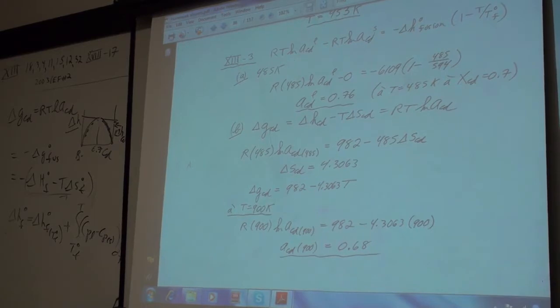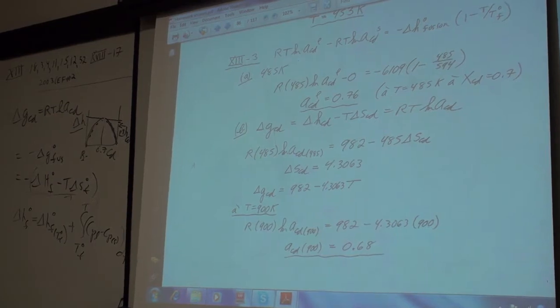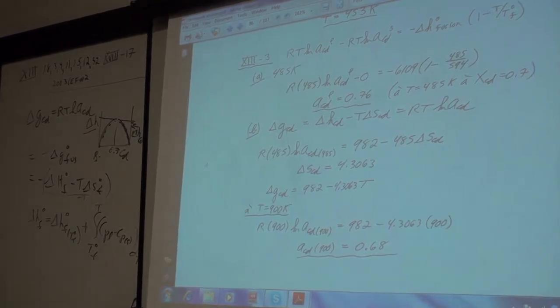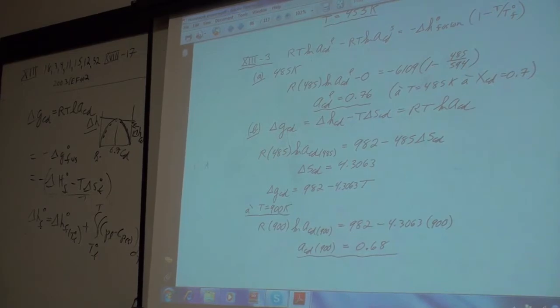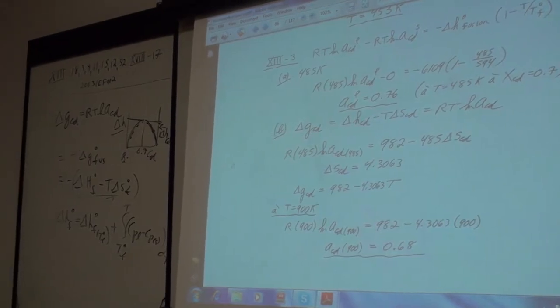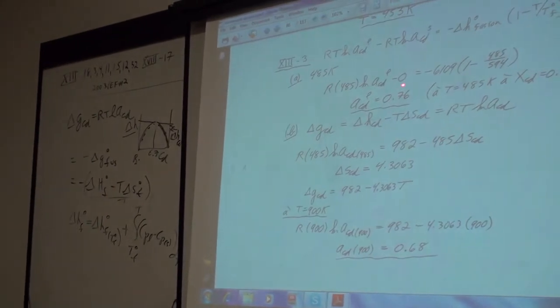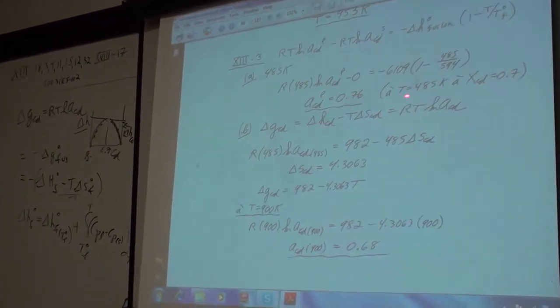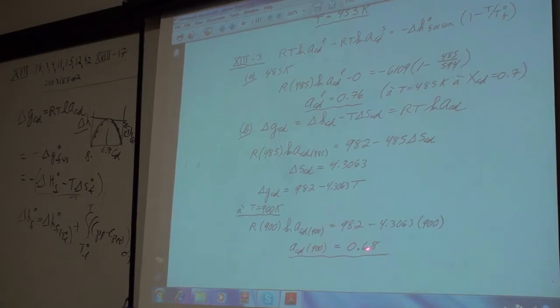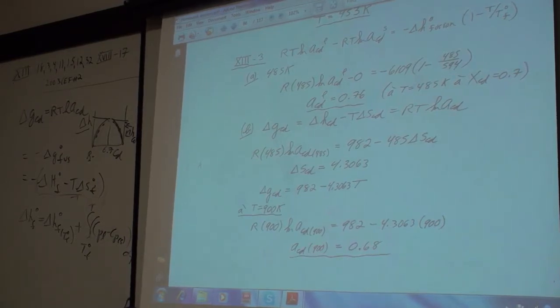There are many assumptions here. We assume the delta Cp was 0 for fusion. That isn't really that necessary. We assume the heat of mixing was independent of temperature. That's a less valid approximation, but probably reasonably accurate. We've assumed the activity of cadmium in the solid is 1 because it's essentially pure solid. Then we see the activity has varied by a reasonable amount. The activity at 485 was 0.76. At 900, it's gone down to 0.68, so it's not a trivial change.